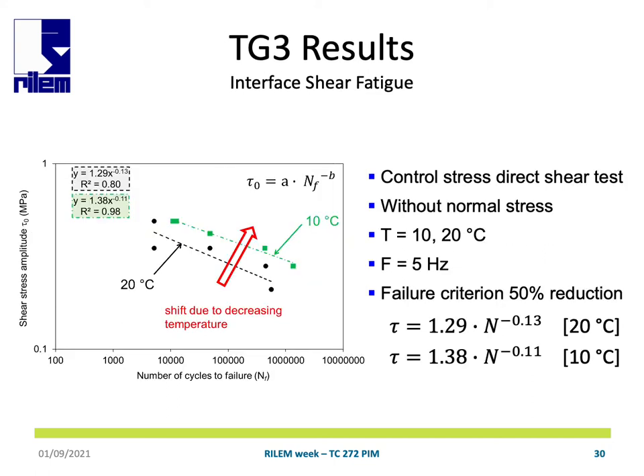Concerning interface fatigue behavior in stress control mode, lifetime appears to be strongly affected by temperature. As an example, for an experiment without normal stress, interface behaves better at low temperature in stress control mode.